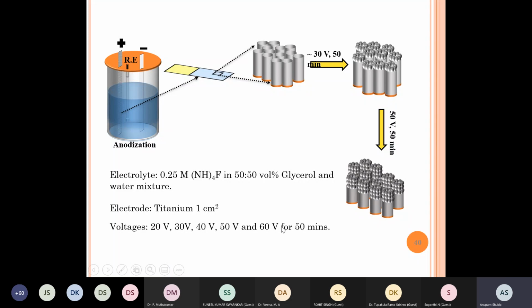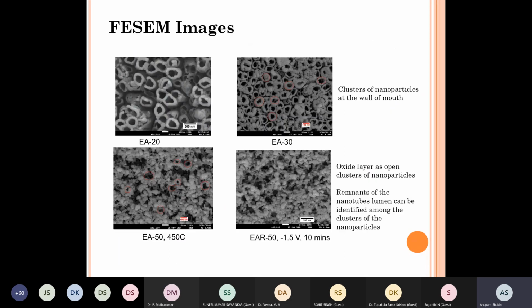Okay, so there are different voltages at which it was oxidized for 50 minutes in 0.25 molar ammonium fluoride solution. So this is the FESEM image. If you see here, you can see more or less regular cylindrical pores of titanium oxide formed over titanium. And if we do it at higher voltage, so this is done at 20. Here 20 EA, for example, is the electrode name. 20 is the voltage at which it was done. So if you do it at higher voltage, as you can see, while here there is not that hint of roughness, the hint of roughness here becomes more, and that is because clusters of nanoparticles are now starting to form over what was earlier a more or less smooth pore wall.